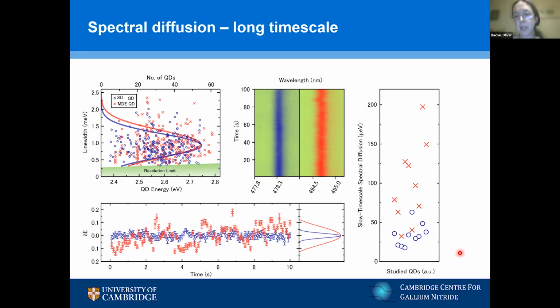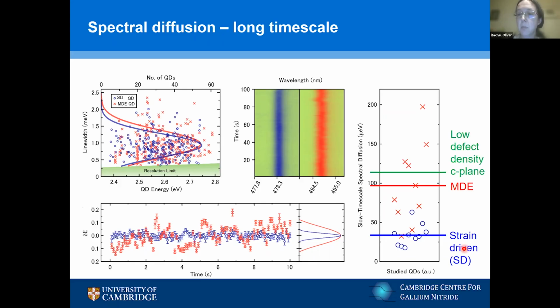Now, what I haven't got on here is anything for the C-plane dots. Are we really seeing an improvement? So I'm just taking the average here as a blue line for the strain-driven dots and a red line for the droplet epitaxy dots on the A-plane. Bringing in C-plane dots, they are slightly worse on average than the modified droplet epitaxy dots, but maybe this isn't the sort of vast change I was hoping to see.